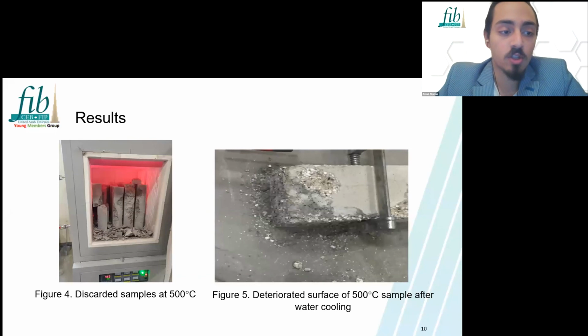Now, another observation, which is very important to note: during the heating process, we had a trial run initially, and we noticed that, just as found in the literature, whenever you put the samples close to each other in the furnace, this will skew your results. So, for example, if you look at the left, we tried putting many samples, in fact 12 samples, close to each other. This had an effect on the concrete itself, and as you can see, at 500 degrees, they all broke because of the temperature gradient. When they're closer to each other, the temperature gradient will have an effect. So we decided to put 6 samples at a time and increase the spacing between them.